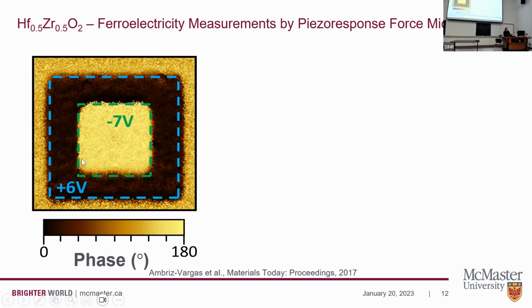So here is a phase image corresponding to the phase of the polarization that we measured on one of our films using piezo response force microscopy. This is the typical image we got, where the bright yellow region corresponds to a region where we applied a voltage of -7 volts. The dark region, also corresponding to the blue square, indicates a region where we applied +6 volts. So here we had a very high positive voltage, and on the other side, a very high negative voltage. We picked those two values in order to be sure that we could switch the material's polarization. When we compare the two regions, we can see that we have a 180 degree phase change between the two, which confirms that we have a switching of our polarization.